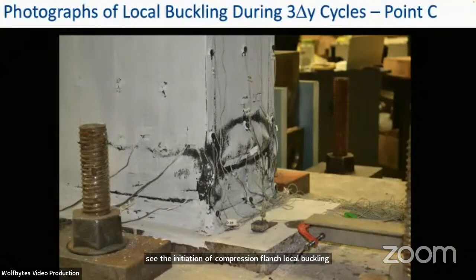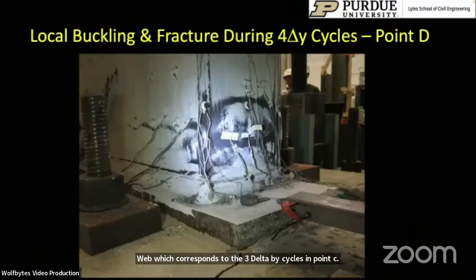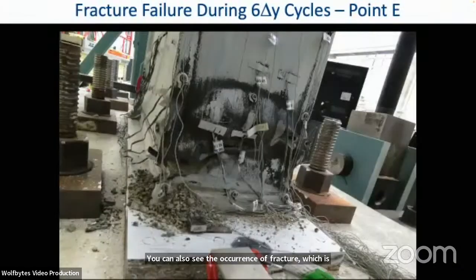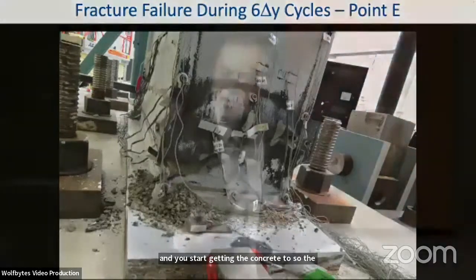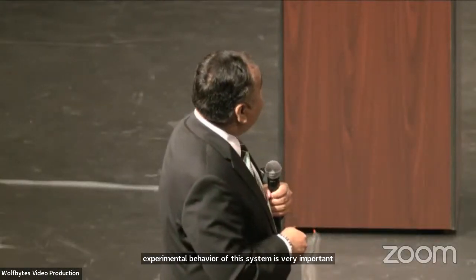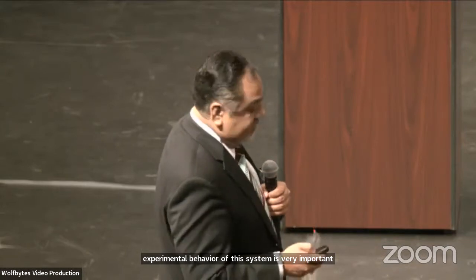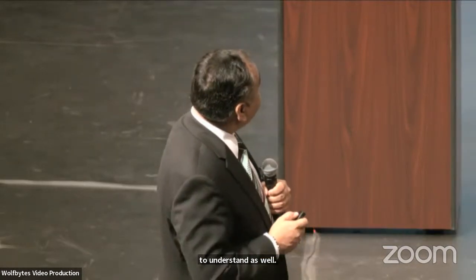You can also see initiation of local buckling in the webs, which corresponds to the 3 delta Y cycles and point C. You can also see the occurrence of fracture, which is point D, right through the flanges right here. And then finally, you get total fracture through the flanges, and you start getting the concrete to ooze out. So the experimental behavior of this system is very important to understand as well. And the experimental data does provide that information to us.